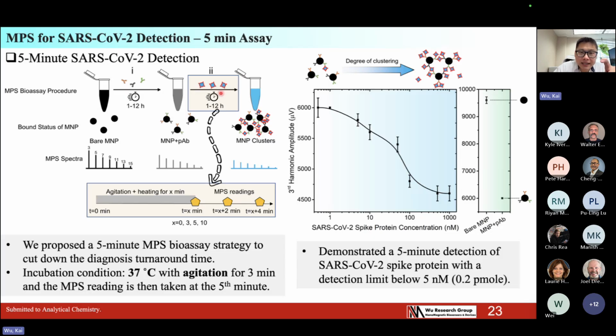In a typical process, people have to wait overnight for the bonding to happen, right? So in our case, we did a shortcut. We apply the mixture of nanoparticle with the biofluid sample under the agitation and heating process. So this mechanical agitation and also thermal heating process will speed up the Brownian motion of particles. The particles will move more frequently. This will increase the bonding chance of the particle to bond with analytes to form clusters. So this process tremendously cuts down the incubation time from 1 hour to 5 minutes.